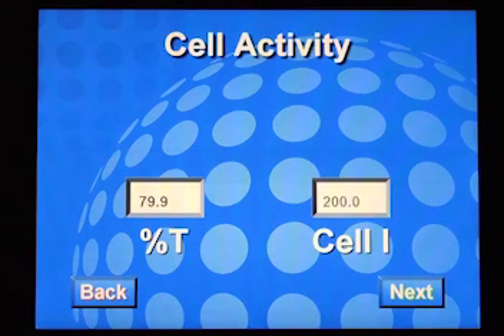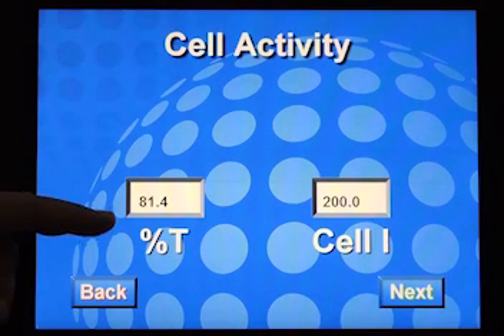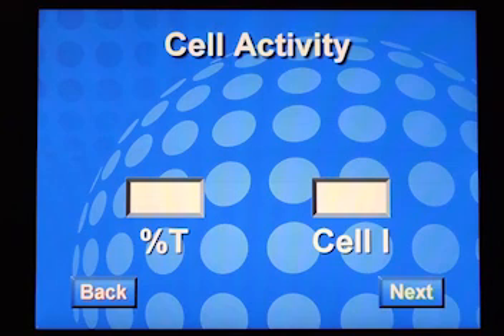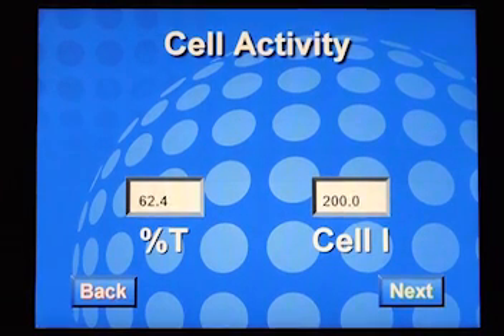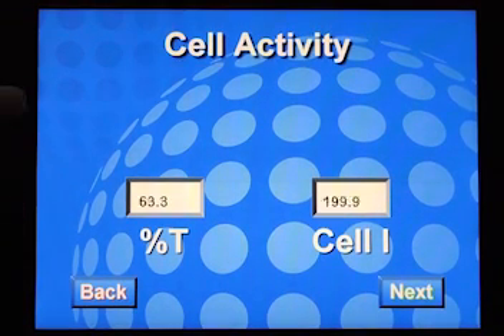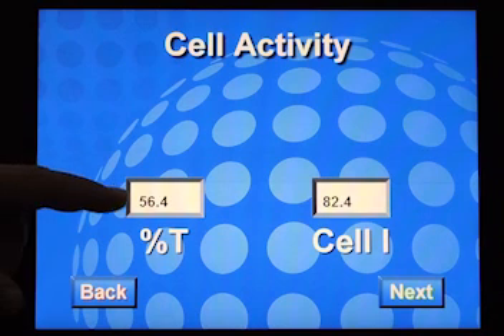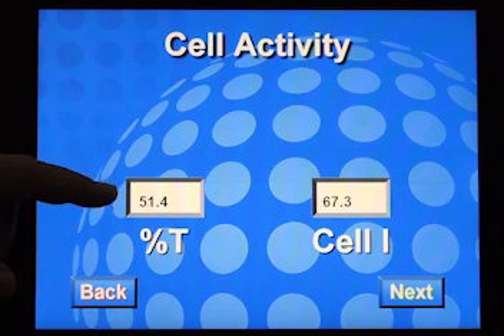The cathode solution will slowly change color and become bluer. The percent T number should decrease to 29.5% plus or minus 0.1. When it does, the titration is complete. While waiting for transparency to decrease, we recommend leaving the coulometer 45 minutes to an hour, even though 29.5 will be reached relatively quickly. This leaves enough time for the system to stabilize.